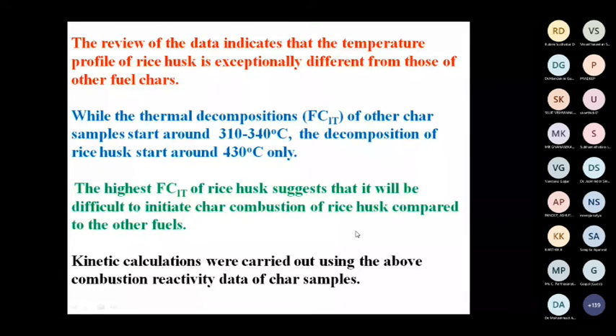The review of the data indicates the temperature profile of rice is exceptionally different from that of other fuel chars. While thermal decomposition of other char samples starts around 430, decomposition of rice starts around 530 only. The highest fixed carbon for rice suggests that it will be very difficult to initiate char combustion of rice compared to other fuels. Based on these char kinetics, the char reactivity TG data, we also made kinetic calculations.